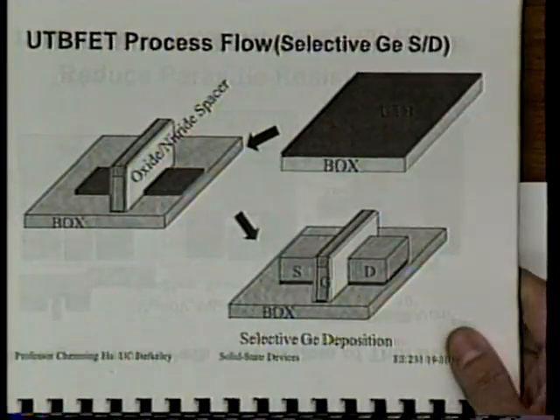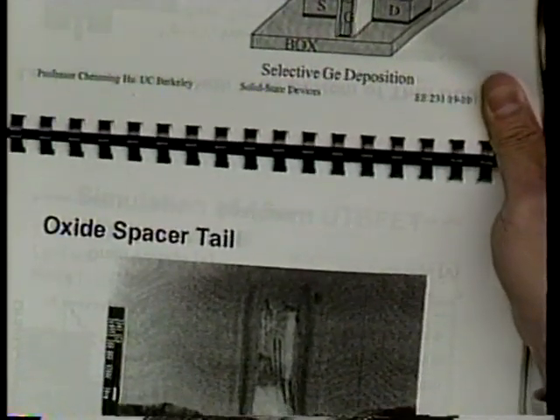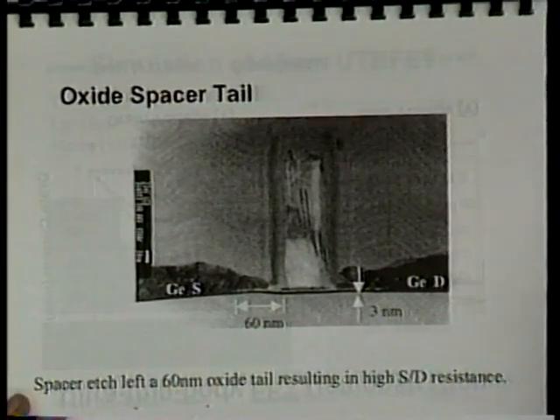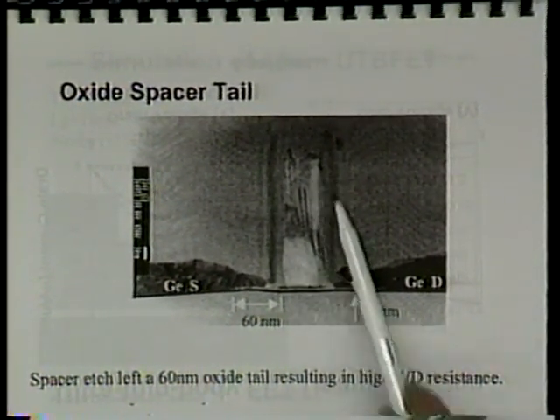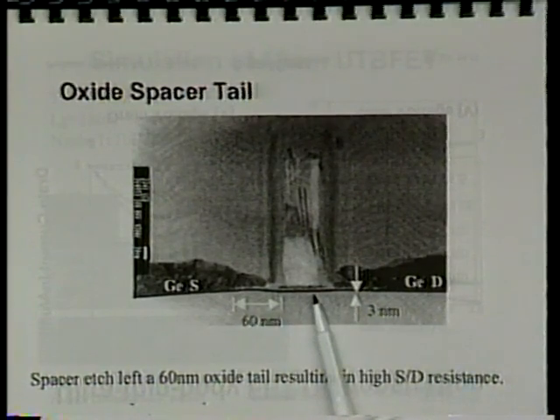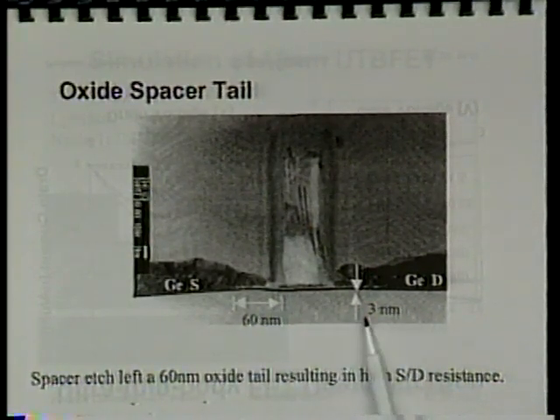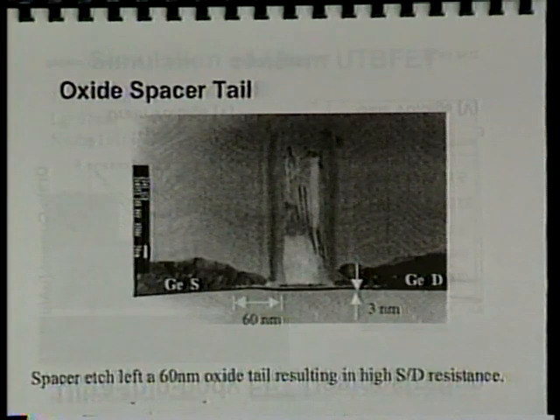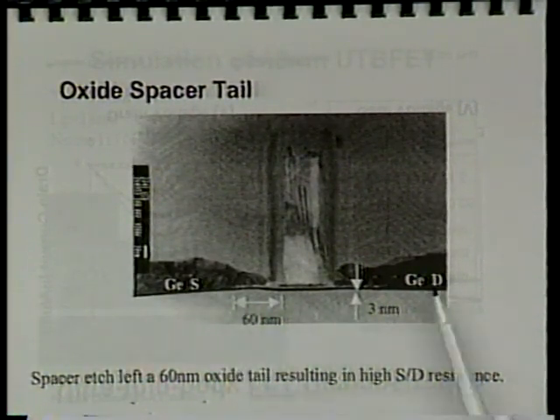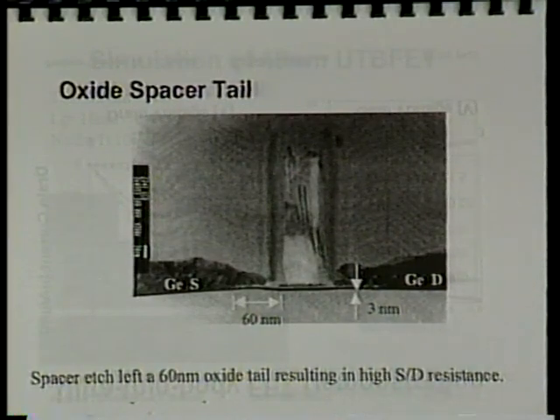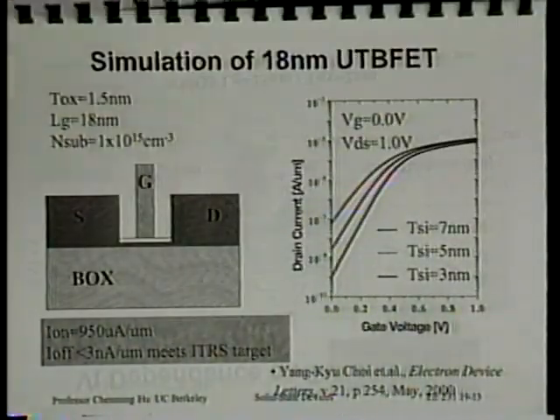It just so happens because of the equipment and expertise we have. All right. So what you see here is the gate with the spacer, the very thin silicon film. Turns out in this case, the SOI film is only 30 nanometer. Not that we really need that. In fact, the best performance did not come from 30 angstrom of a film, but just to illustrate using this TEM picture, he was able to make the silicon film as thin as 3 nanometer. And this is the raised germanium source drain. See that?